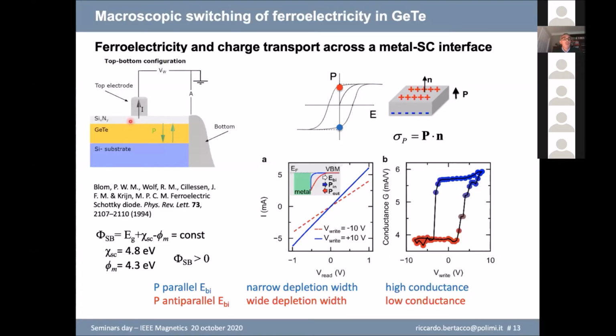And you can now look at the IV curve. It turns out that when you pulse your structure by applying a positive or negative voltage, in this case plus 10 or minus 10 volts, you obtain a different IV curve. And typically you have a higher conductance in the case of a positive pulse applied at the top electrode. What's the reason for that? The reason is that you are changing the barrier profile of the Schottky barrier, the interface between your semiconductor and your metal. For a positive applied pulse, the polarization is pointing parallel to the built-in electric field, and you have a narrow depletion width, which means a high conductance, as in this case.